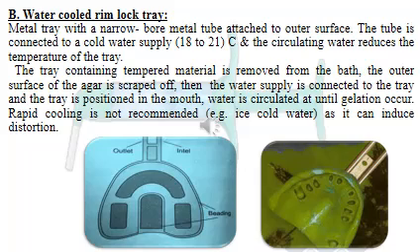The outer surface of the agar is scraped off. Then the water supply is connected to the tray and the tray is positioned in the mouth. Water is circulated until gelation occurs. Rapid cooling with ice cold water is not recommended, as it can induce distortion.